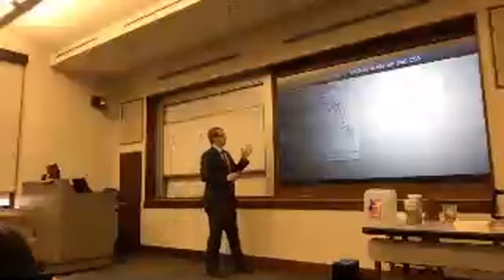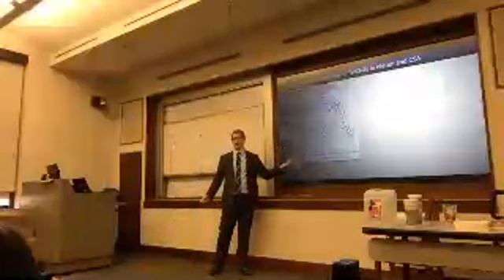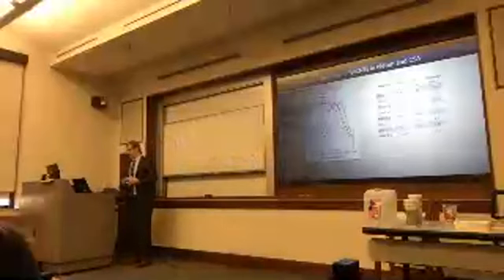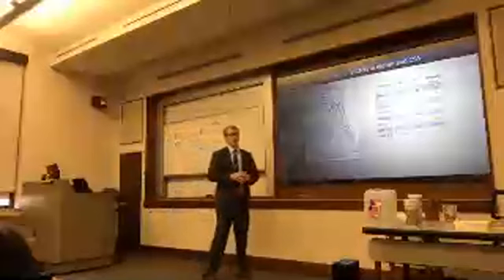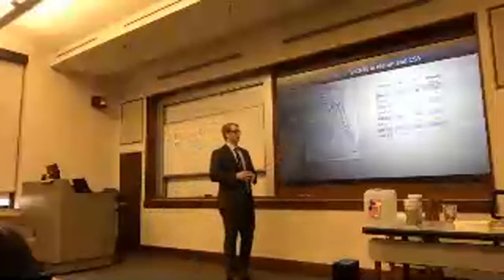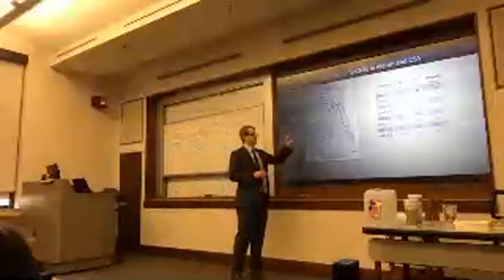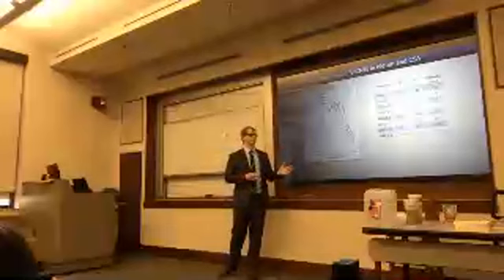So we can do this experiment with some of the materials in our lab. Here I'm showing the G peaks for 4 different single-wall carbon nanotube samples. Each of these materials in air has a G peak right around 1590. So you can see how their G peak shifts to different extents. In this case, sorry, they're dissolved in oleum. And we can quantify those shifts. If we go through this data, HIPCO, which has a diameter of about 1 nanometer, shifts in oleum by 28 wave numbers. CG301X, which is a smaller diameter nanotube of about 0.8 nanometers, shifts by 24 wave numbers.